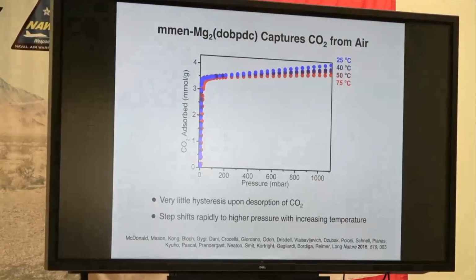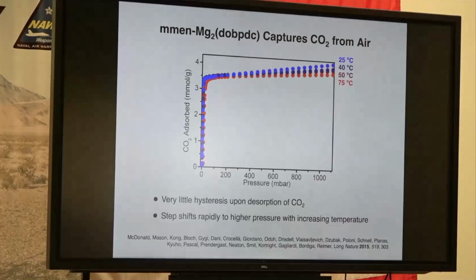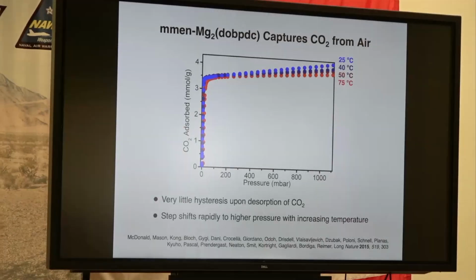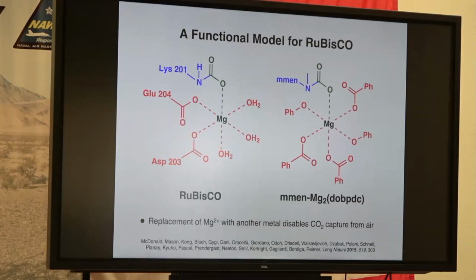And so the response in terms of CO2 pressure is very nice. You see a steep uptake at low pressures, well below the concentration of CO2 in a flue gas, under flue gas conditions. And this is about 18 weight% CO2 uptake in the materials. So very high uptake of CO2 under these conditions. So this is very much a functional model of Rubisco, because the same thing is happening locally. We're getting CO2 inserting between the magnesium and the amine. And indeed, this MOF can capture CO2 directly from air, where it's 420 parts per million in concentration.